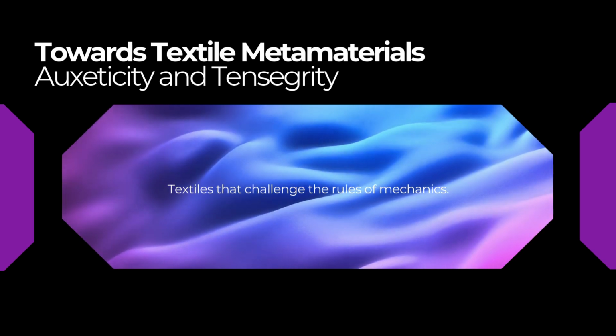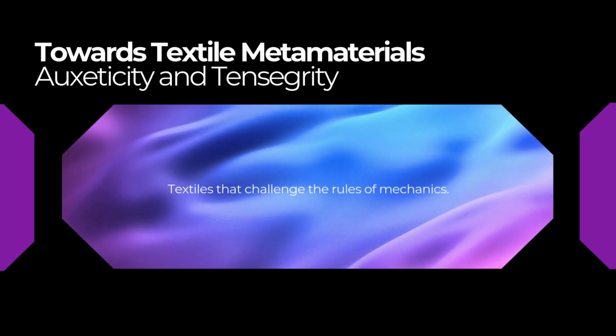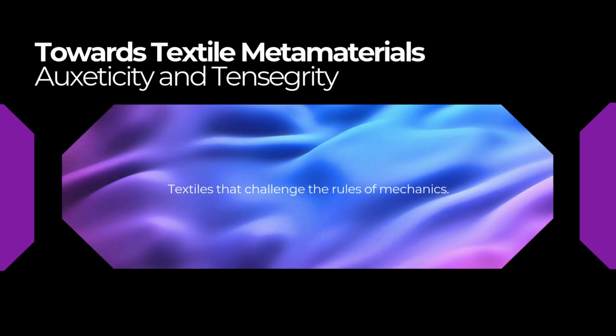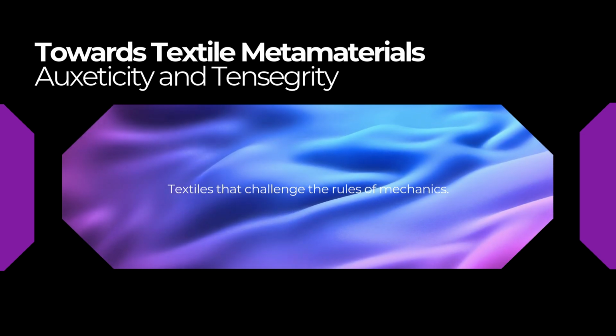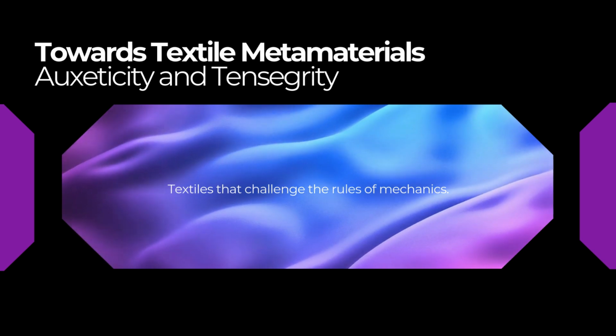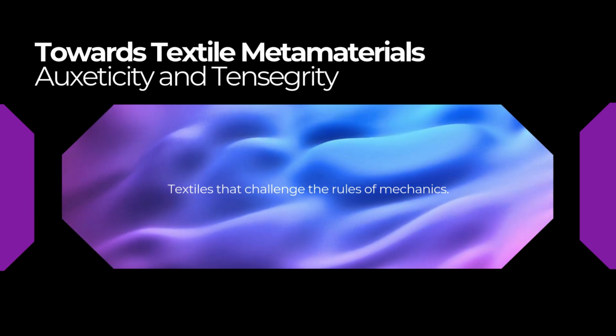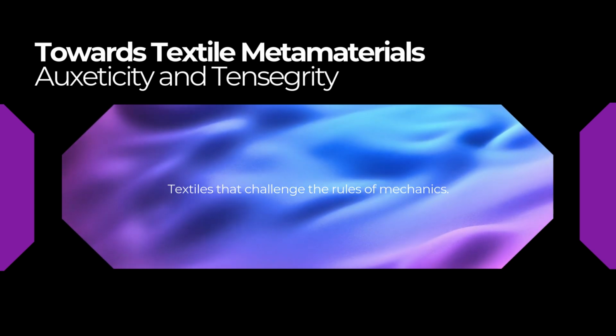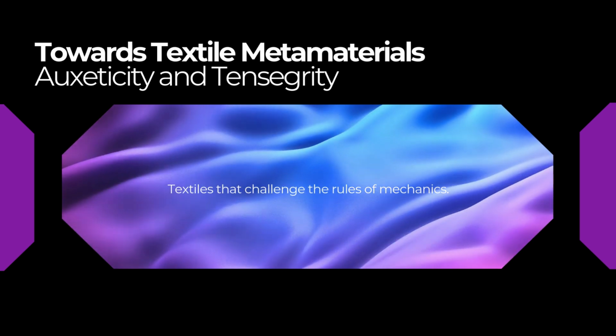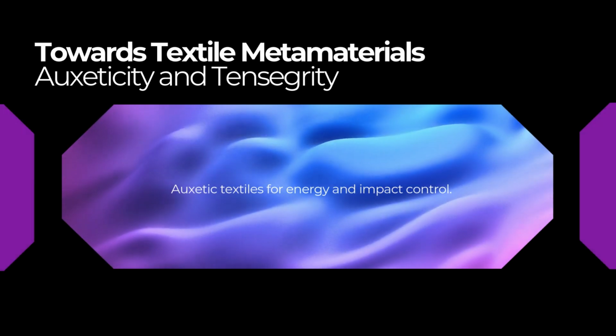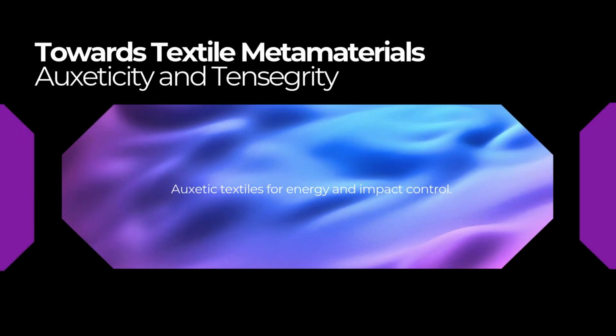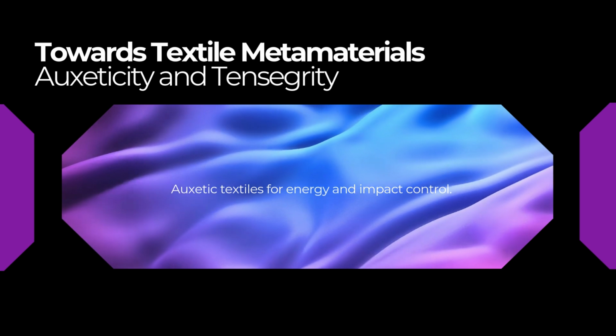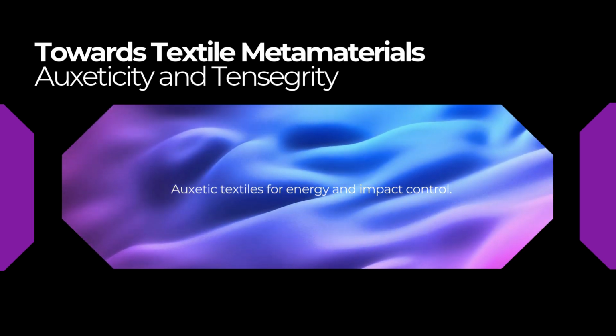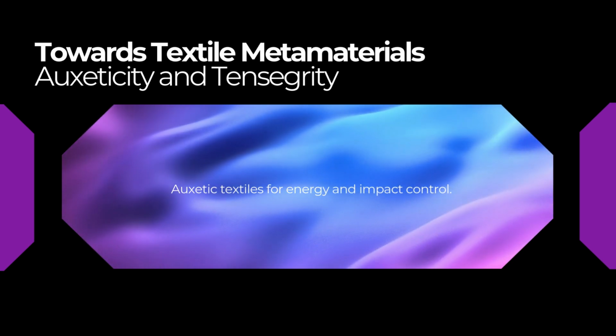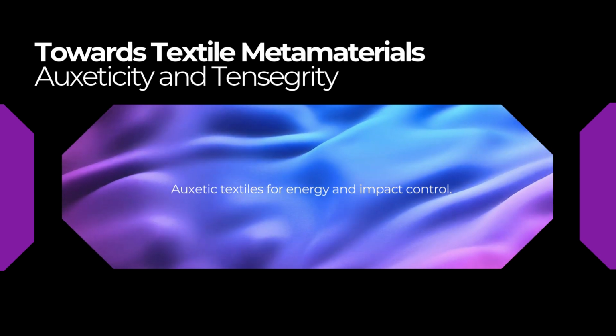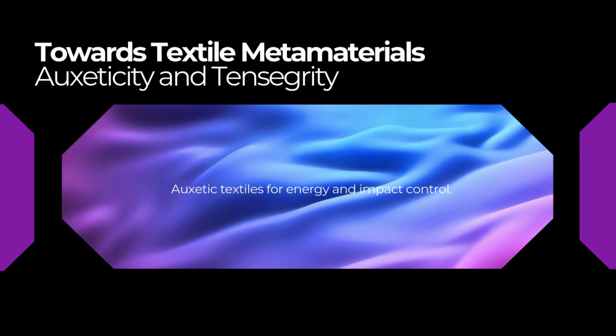Okay, draw that analogy for us. So micro-CT imaging confirmed the felt had these distorted, rotated fiber columns. These columns, which are under compression from the thermal processing, they're the struts. They're analogous to the rigid curvilinear cylinders in a tensegrity structure, and the surrounding fibers and those fused bonds which hold it all together, they're the tensioned cables. Exactly. The whole messy network is self-stabilizing, held in equilibrium by this balance. The stiff felt is basically a naturally occurring or maybe accidentally manufactured micro-tensegrity system.